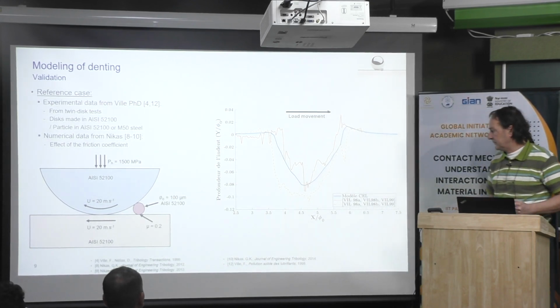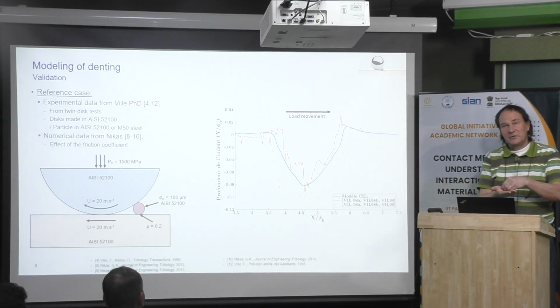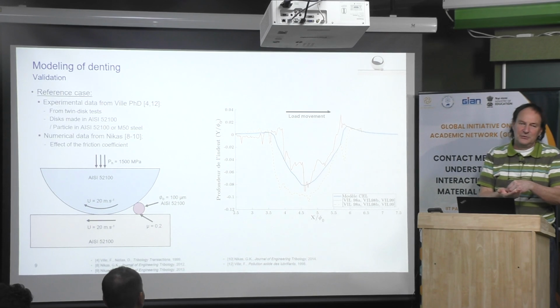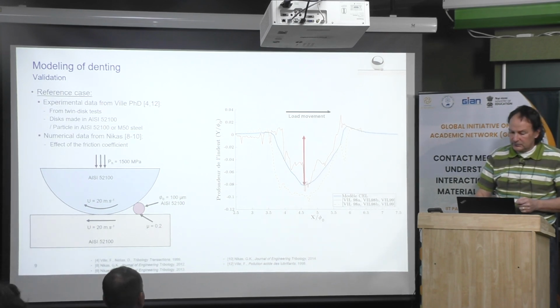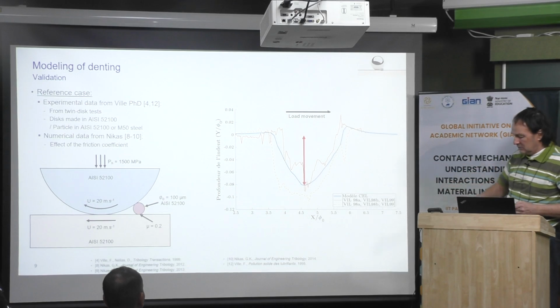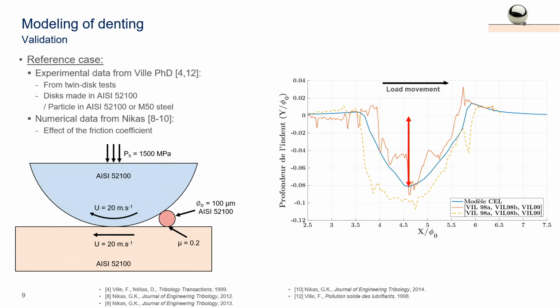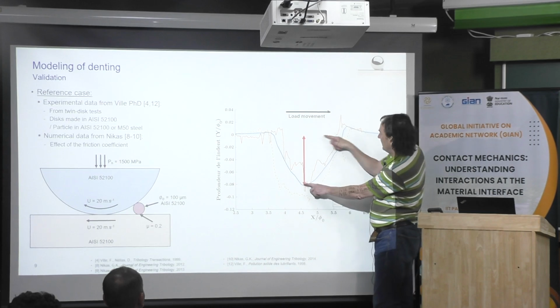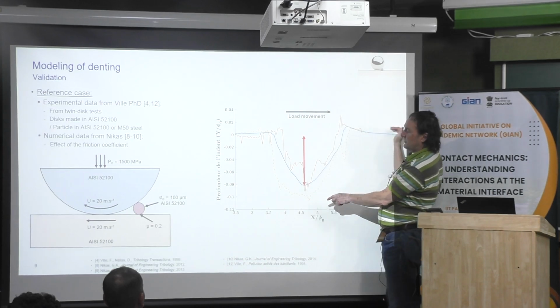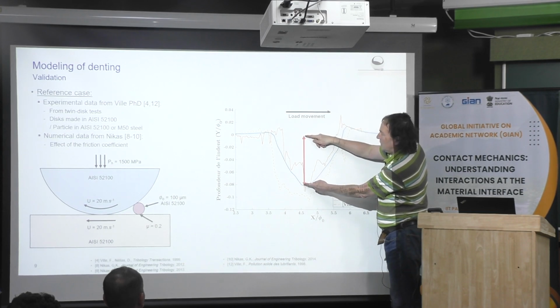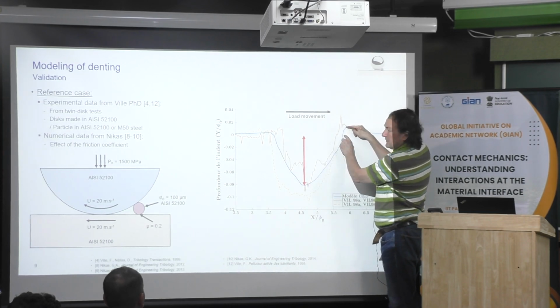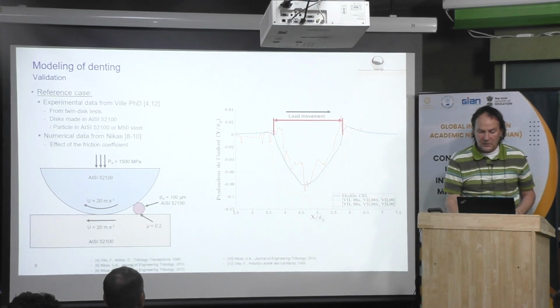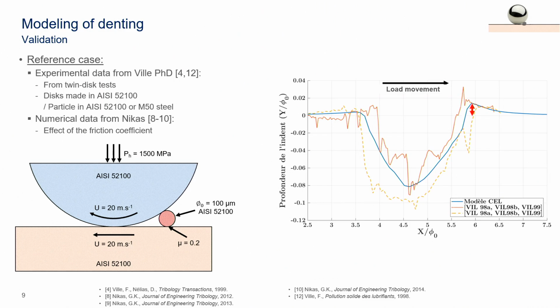There is some dynamic effect. When you do indentation to reproduce an artificial dent, it is not the reality, something different. You can see the depth here, I don't know if it is indicated. This is dimensionless. Then the main parameters are the dent depth, which is measured from the surface far from the dent. After you have the diameter, and you have the shoulder height. Then you have three interesting parameters. This one and the shoulder height on the right, for example.